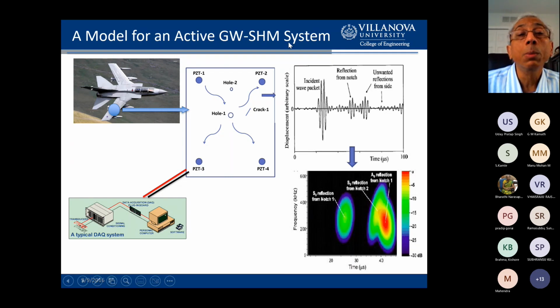And then you perhaps have defects inside in the region of interest. The ROI, or region of interest, is a phrase that I'll be using quite a bit over the next few minutes. So you could have holes, maybe they're pre-existing holes, or maybe there are holes that arise because of a bird strike or whatever, or cracks. So any kind of defect that's over here. And so these transducers are periodically excited, and the signals are picked up. And then a typical signal looks like this. You have the incident wave, and then reflections from the defects, and then unwanted reflections from the edges of the plate. All that is mixed together, and somehow you've got to take that information and decipher it. Well, with this sort of scenario, you would have multiple transmitter-receiver combinations.